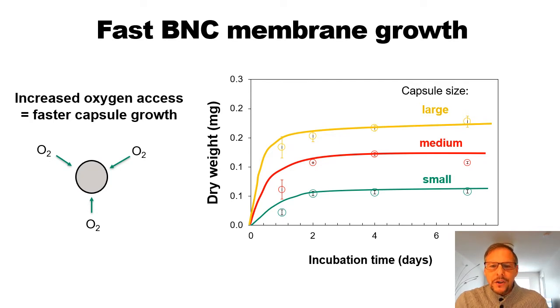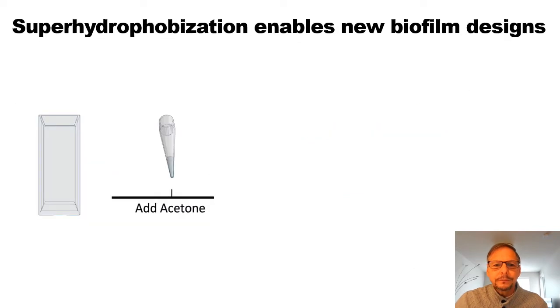And also you will appreciate that depending on the size of the droplet of the culture medium that we deposited on the surface, you can have larger or smaller particles. In all cases, what we're using is oxygen or air that is entrapped at the interface for the microorganisms to be able to undergo the aerobic process of producing the cellulose as a biofilm.